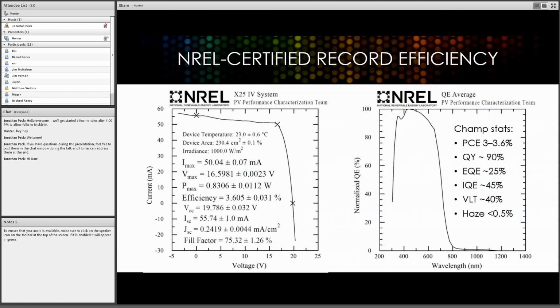As I mentioned, it behaves a lot like a module, with about 20 volts VOC in this case, and almost 60 milliamps, and this is over about a 6-inch by 6-inch device. So that would translate into roughly 3.4 watts, I believe, per square foot, which is pretty good. We think the target, or at least the milestone to commercialize, is around 50 watts per square meter, or around 5 watts per square foot, and we're almost there.